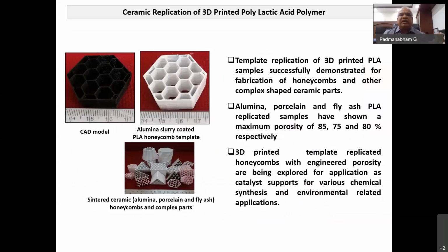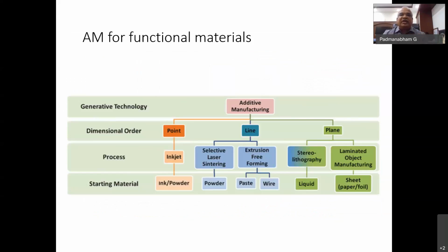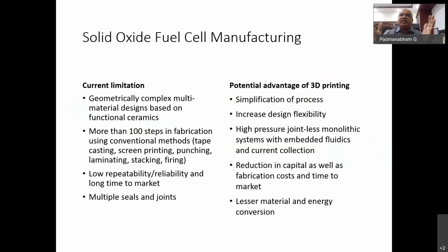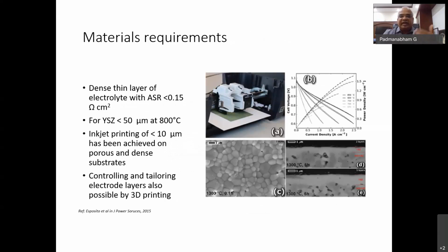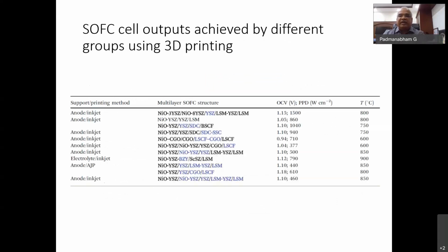Even ceramic replication of 3D printed PLA polymers is another approach. And then functional materials are also additively manufacturable. I'll give an example. What is a solid oxide fuel cell? It is an anode supported or electrolyte supported electrolytic cell. Basically, it's a ceramic material. On one side, you have nickel and yttria stabilized zirconia, and on the other side you have lanthanum strontium manganate. And this is 3D printable using these three different materials. You have enough literature available, and comparable open circuit voltage is achievable using 3D printing of solid oxide fuel cells.